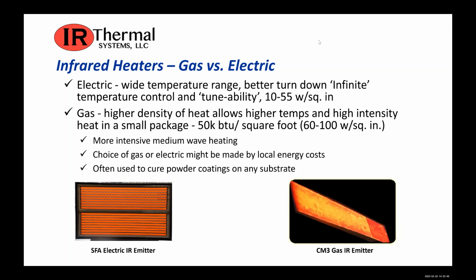With gas, you have a higher density of heat that allows higher temperatures and high intensity heat in a small package, the 50,000 BTU per square foot, which is 60 to 100 watts per square inch. So it's quite a lot more than the electric heater. So it's more intensive medium wave heating. The choice of gas or electric might be made by local energy costs. Those things are changing all the time, but it also varies by location in the world. And they're often used to cure powder coatings on any substrate.